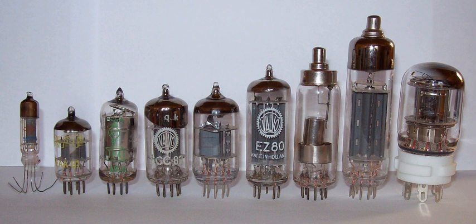An arc can be caused by applying voltage to the anode plate before the cathode has come up to operating temperature, or by drawing excess current through a rectifier, which damages the emission coating. Arcs can also be initiated by any loose material inside the tube, or by excess screen voltage. An arc inside the tube allows gas to evolve from the tube materials, and may deposit conductive material on internal insulating spacers. Tube rectifiers have limited current capability, and exceeding ratings will eventually destroy a tube.